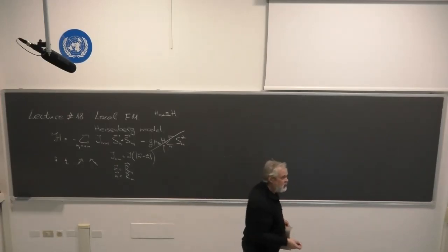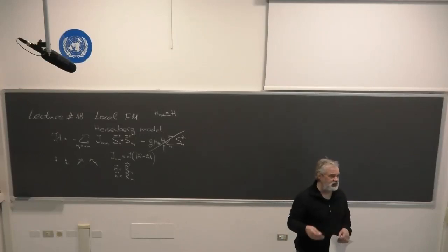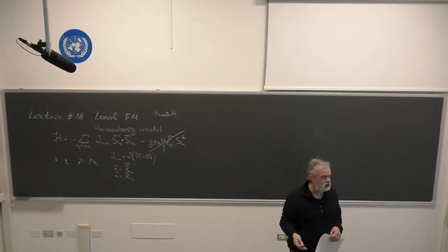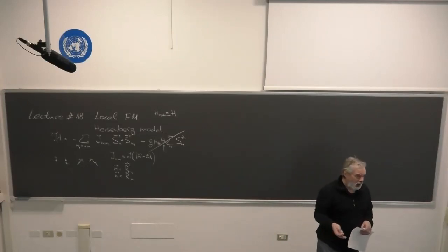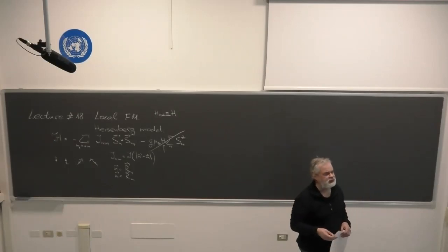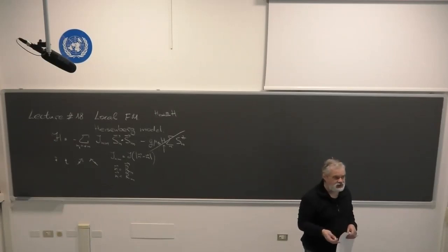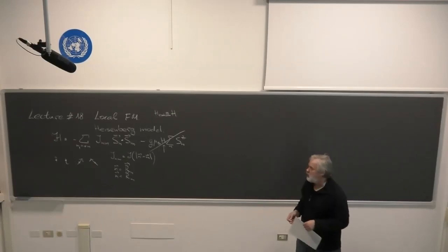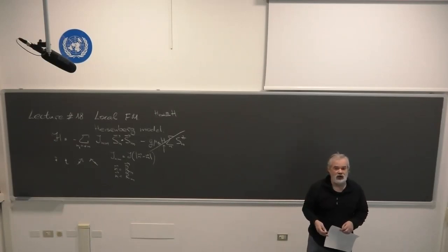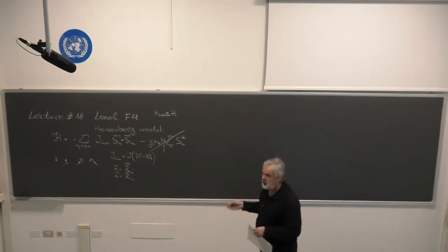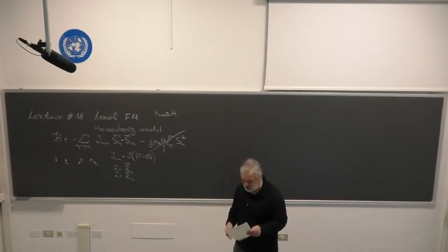However, it can also happen that due to the Ruderman-Kittel-Kasuya-Yosida interaction, RKKY interaction, which we know results in a 1 over R cubed dependence, the same way as magnetic dipole interaction, it can also be long range. It doesn't exclude this. There are different mechanisms of interaction between spins. However, the most common one, as I said, typically results in the interaction between nearest neighbors.